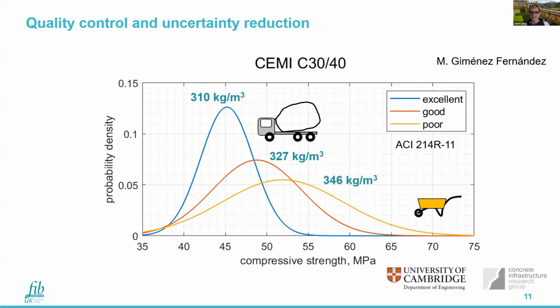If we look at these ideas, and this is work that one of my students, Ma, has kindly prepared for me, if we take an example, and we can take other examples, but looking at a CEM I C30/40 mix, let's think about the idea of quality control. So in this plot, on the vertical axis we have probability density, and on the horizontal, compressive strength. These probabilistic distributions, normal distributions, show us that within either excellent, which is the blue, good, which is the orangey color, or poor, which might be that we have a few shovelfuls of cement and aggregates and sand and a bit of water, we see that we get very different distributions.